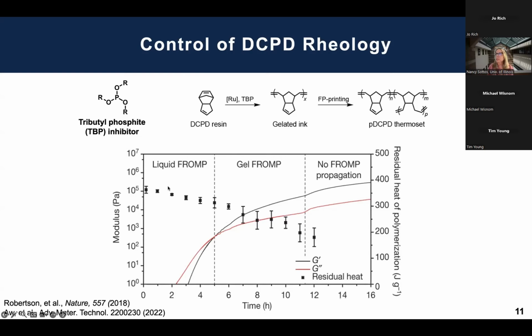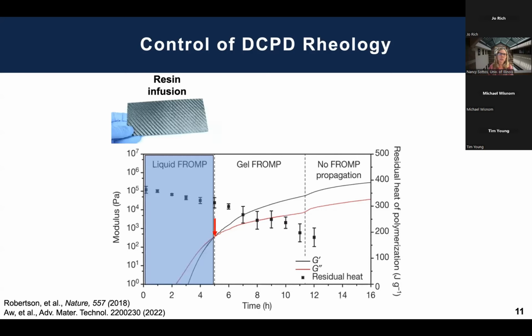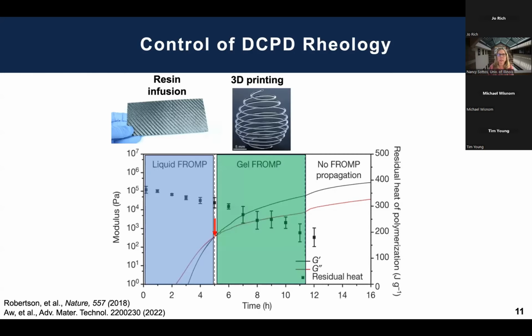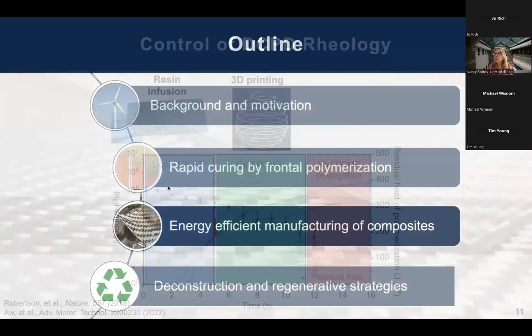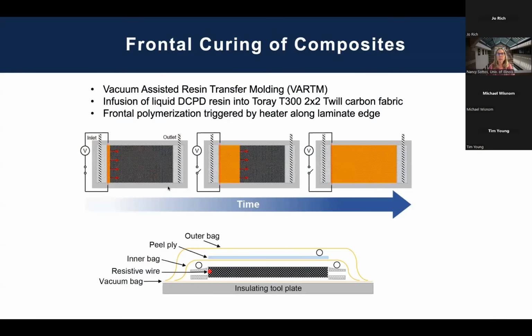And in these different stages, early on with this particular formulation, if we work before 5 hours, we're able to infuse this resin into composites. We have plenty of time to do that and create high quality composites. That's what I'm going to talk about today. If you wait a little bit longer and you get into the gel state, you have a material that has the right rheology for 3D printing. That's something I'm not going to talk about. And of course, if you wait even longer, in this case, it was 11 hours of pot life, you won't get this frontal, there's a background reaction that occurs and you just get an undesirable material and no capability for frontal polymerization.